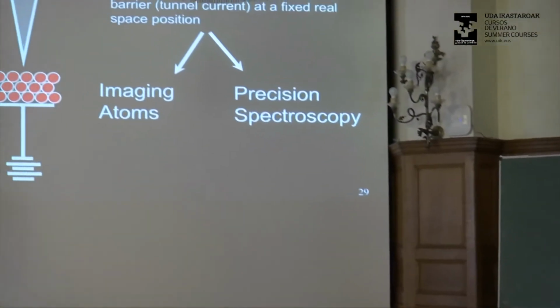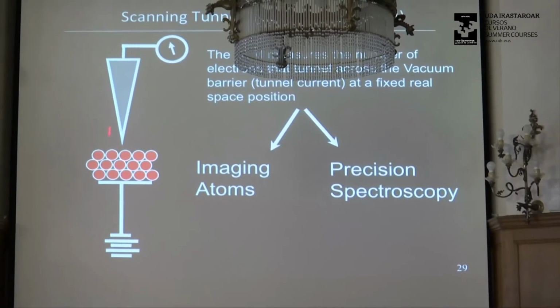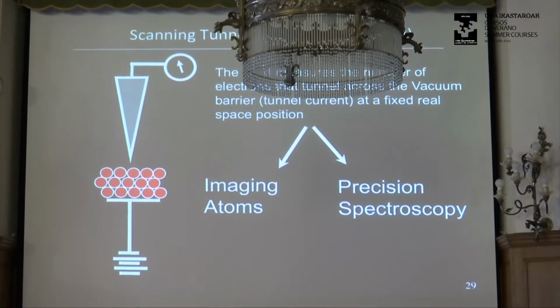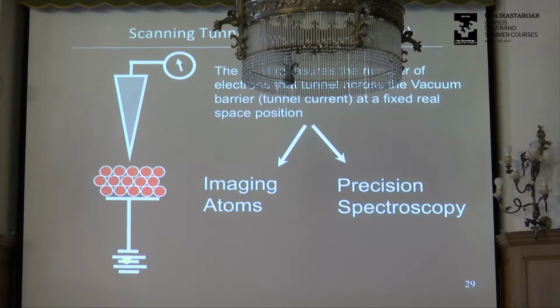Before that, let me show you how STM works. It's a very simple technique. I think most of you must be familiar with it. You have a very sharp tip that you bring close to the surface of the sample that you want to look at, and you turn on a potential difference between the tip and the sample, and electrons tunnel across this vacuum barrier from the tip to the sample or vice versa. And this is exactly what we measure. We measure this tunnel current, and we can measure the tunnel current as a function of bias voltage, as a function of position, and as a function of magnetic field and so on, but our only measurement is actually the tunnel current.